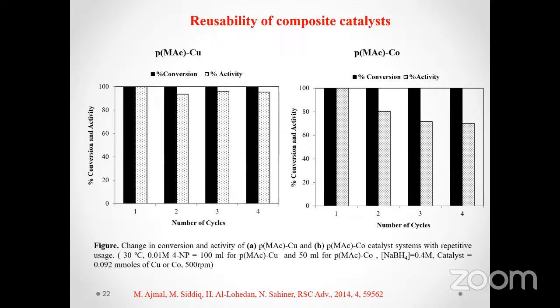Another important feature of the catalyst is its reusability, that is, for how many cycles you can reuse a catalyst. The greater the number of recycles, the greater the effectiveness or efficiency of that catalyst. In this study, it was observed that in the case of copper and even cobalt, the catalytic activity was observed up to 4 cycles. However, in the case of copper, a very small decrease of just 10% was observed in the catalytic activity, even in the 4th cycle. And in the case of cobalt, a gradual decrease in the catalytic activity was observed.